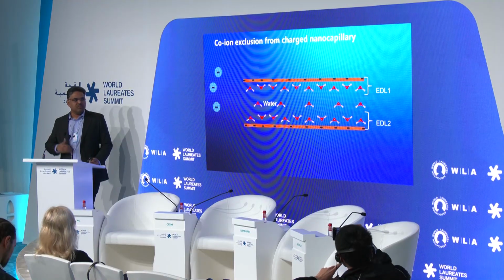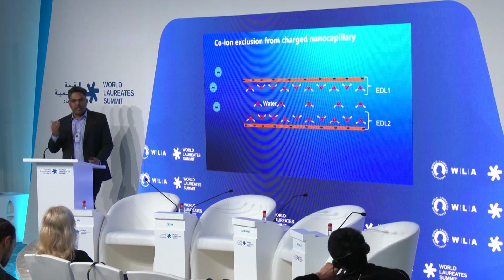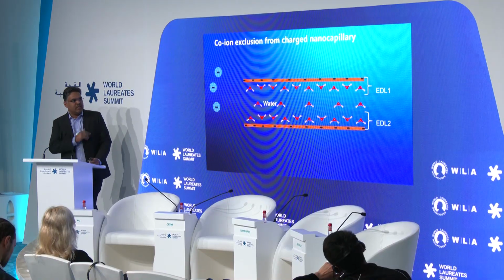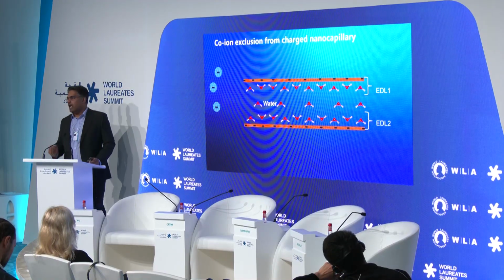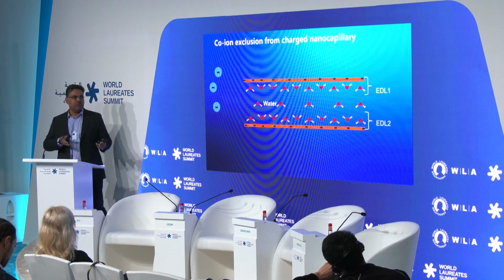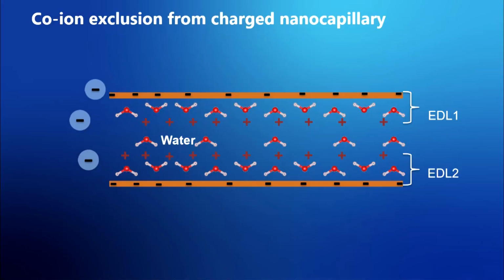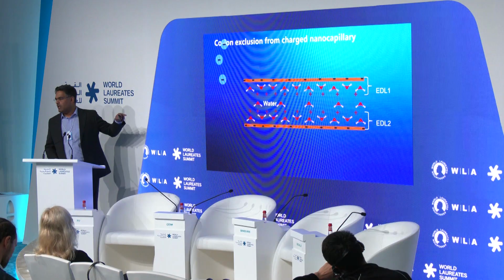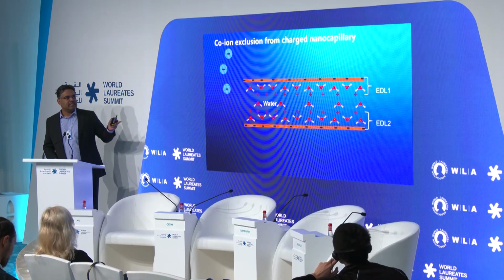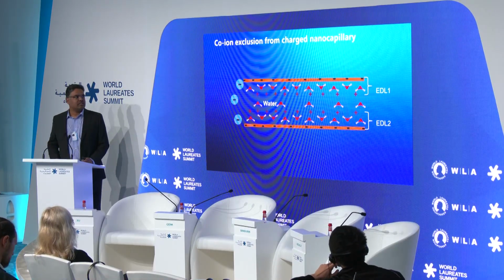Now if you think about our membranes or graphene, they are actually 2D capillaries. And if you think about such a capillary with a negative surface charge on the membrane, and you put it in water, typically it forms an electrical double layer. Because of the negative charge, if you put an external ion into the membrane feed with the same charge, we call it a co-ion, that cannot enter the membrane because of electrostatic ion exclusion. This is also known before, the ion exclusion phenomenon. Because of the same charge, the ion cannot enter because of electrostatic repulsion.